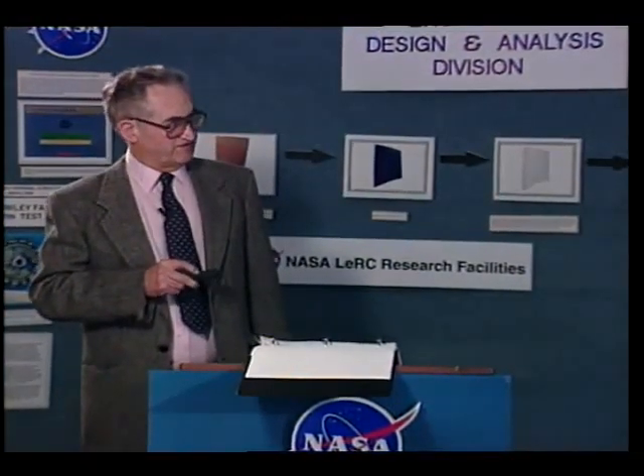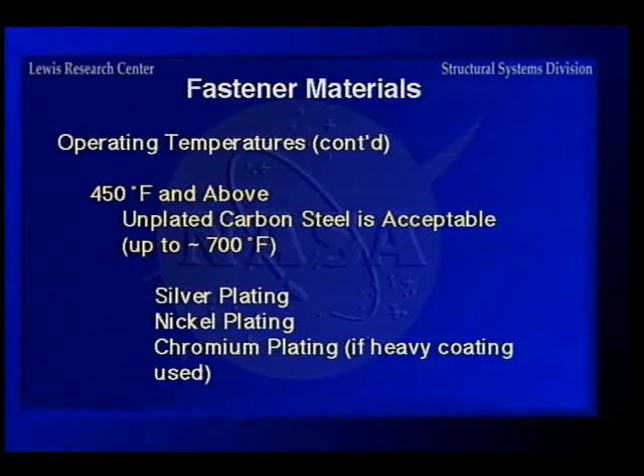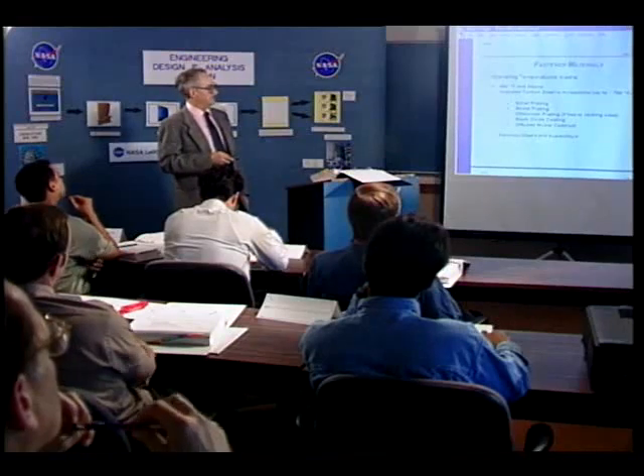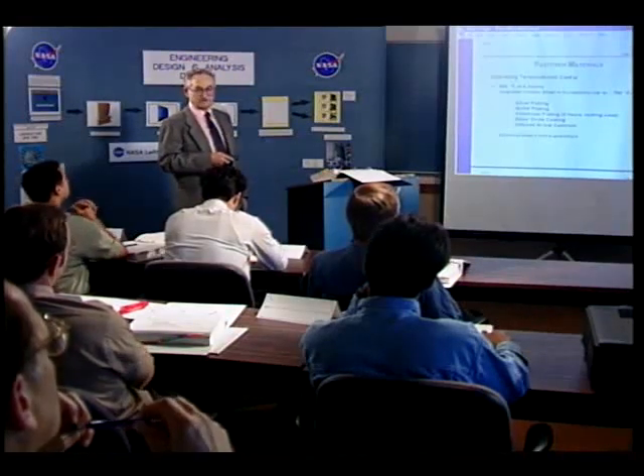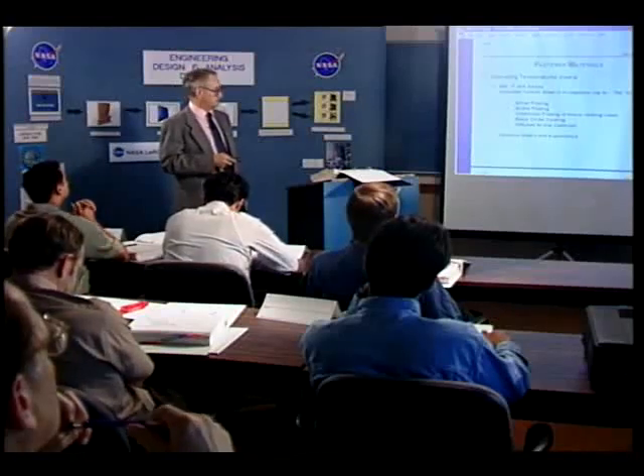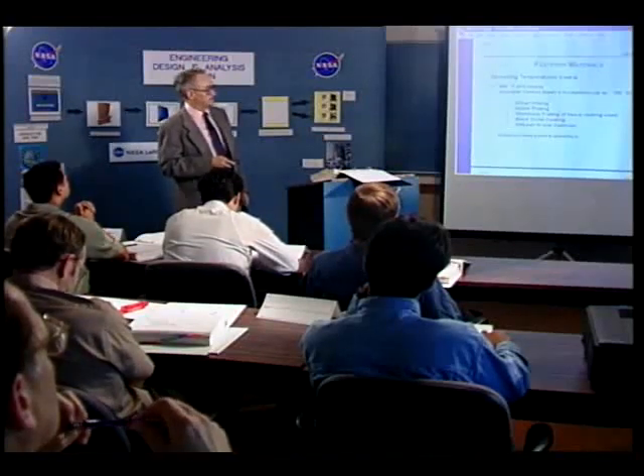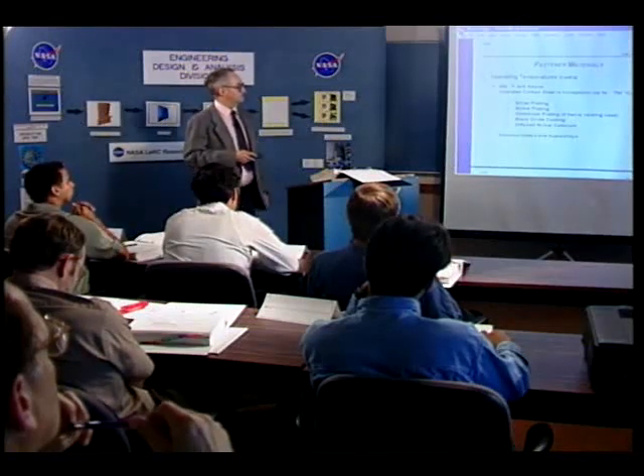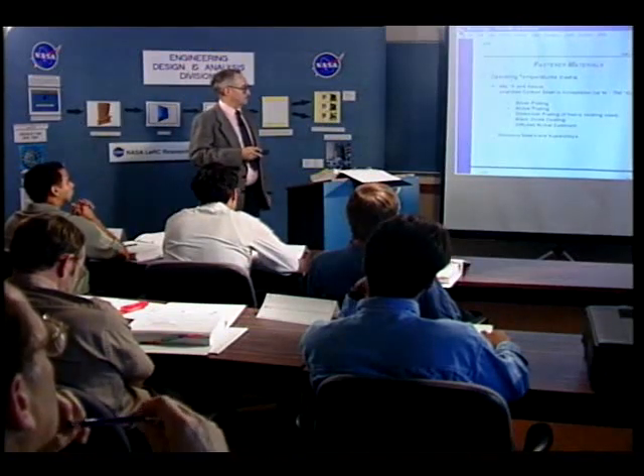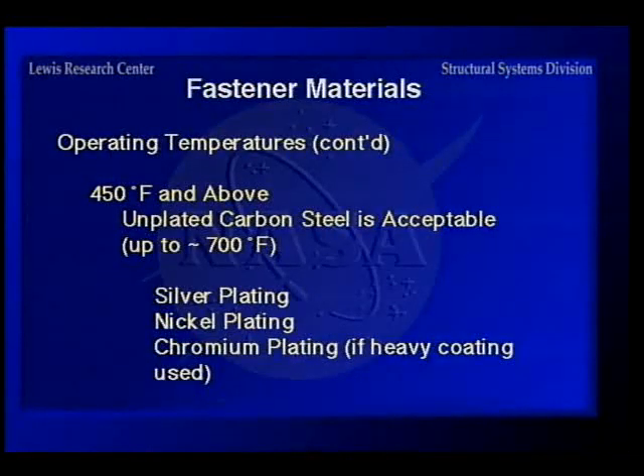Now, for the 450 and above, believe it or not, you can use unplated carbon steel up to about 700 degrees because the only thing you're looking at there is how much does the allowable drop on it for the temperature. So if you go in one of the books like Mil Handbook 5, you can find temperature curves for carbon steels, and you find it, use it. But you see, the reason I'm saying unplated is that an awful lot of the platings for steels burn up before you get to that temperature. So these are some of the ones that don't hurt you, at least.